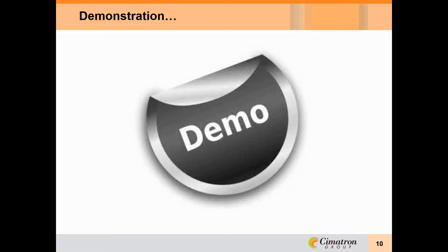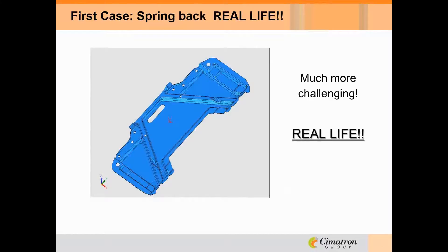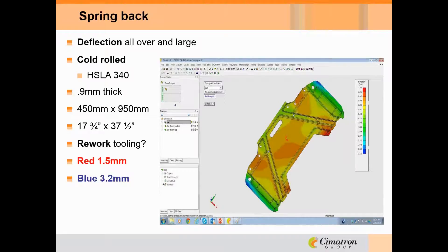Let's bring some real-life cases as examples. This panel has been modified slightly, but the scenario and problem are captured here. Taking it into analysis, you can see deflection all over — as much as 1.5 millimeters in one direction shown in red and 3.2 millimeters in the opposite direction. Dealing with cold rolled HSLA 340 at approximately 0.9 millimeters thick — roughly 20 gauge — the overall size is 17.75 by 37.5 inches. That's a big piece of steel making this panel.